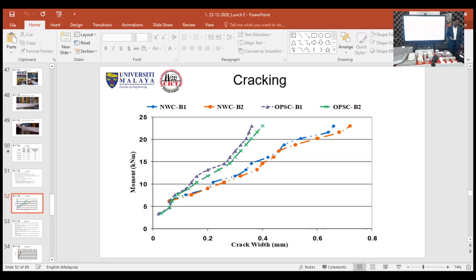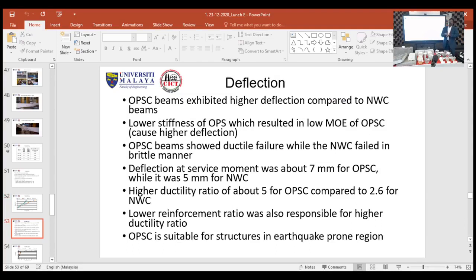As I mentioned, a high ductility ratio of about 5 for the oil palm shell concrete beam compared to 2.6 for the normal weight concrete enabled us to understand, oh, this material has ductility characteristics. Also, we can use this kind of oil palm shell concrete in earthquake prone regions, because the failure of this type of concrete is not catastrophic. It's not brittle failure. Because of this ductility, the failure mode is ductile.